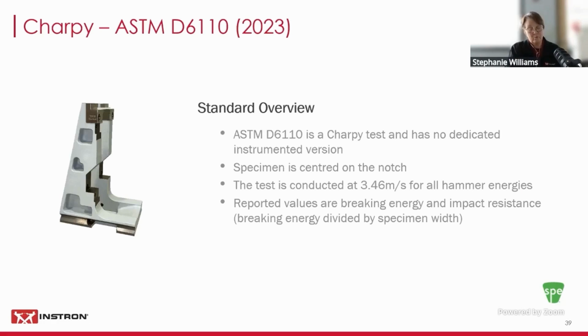The sample will be 127 millimeters long. It will be 12.7 millimeters deep. And then its thickness can vary anywhere from 3 millimeters to 12.7. The standard does state the preferred thickness should be 6.3 millimeters, and that's to prevent any twisting or crushing that can happen with the thinner 3 millimeter thick sample.